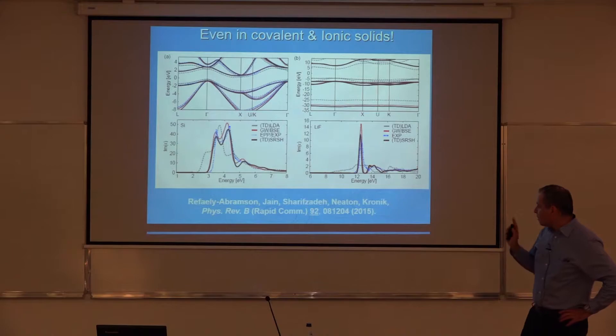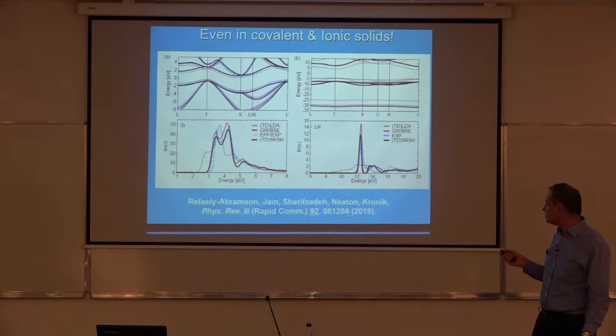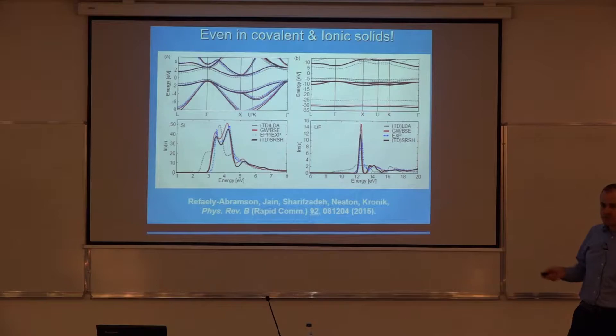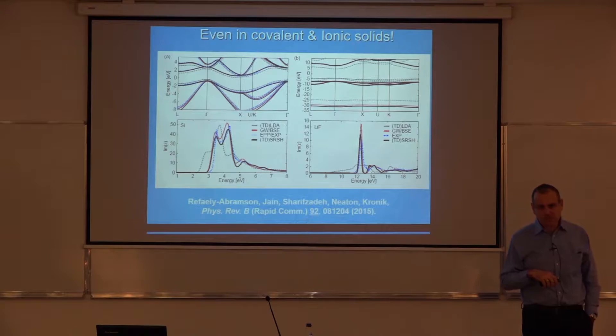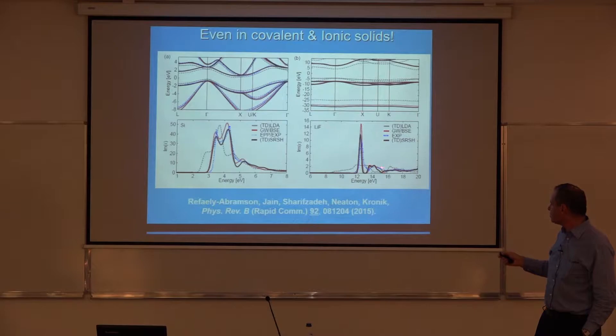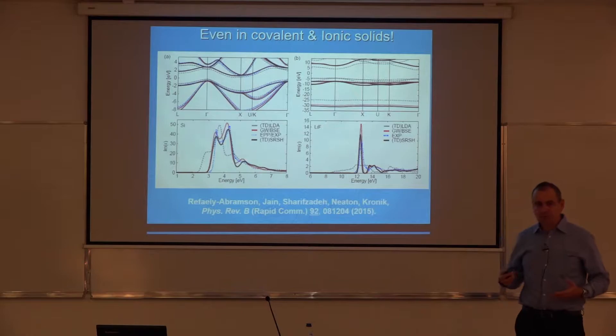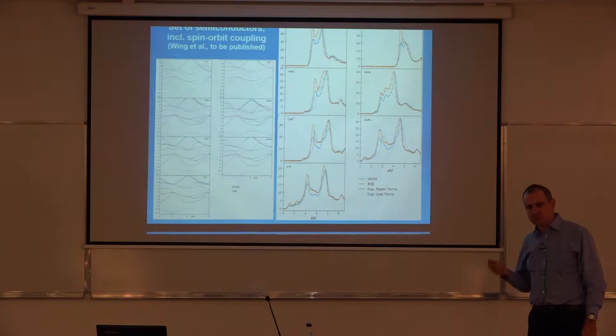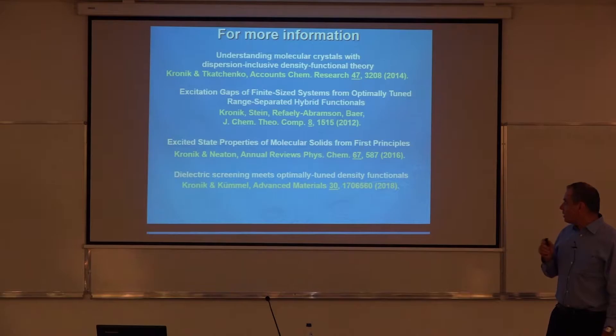The same idea can even be extended to conventional solids with one parameter that fixes the gap — still semi-empirical, and we're trying to get rid of it. This is most pronounced for lithium fluoride, where experiment tells you there should be a sharp excitonic absorption feature. Standard time-dependent DFT thinks the absorption is all over the place — the agreement between theory and experiment can be described as non-existent. But with the new approach, we're doing very well, describing experiment as accurately as many-body perturbation theory. Newer unpublished work on a broader set of semiconductors, including spin-orbit coupling, continues to work.